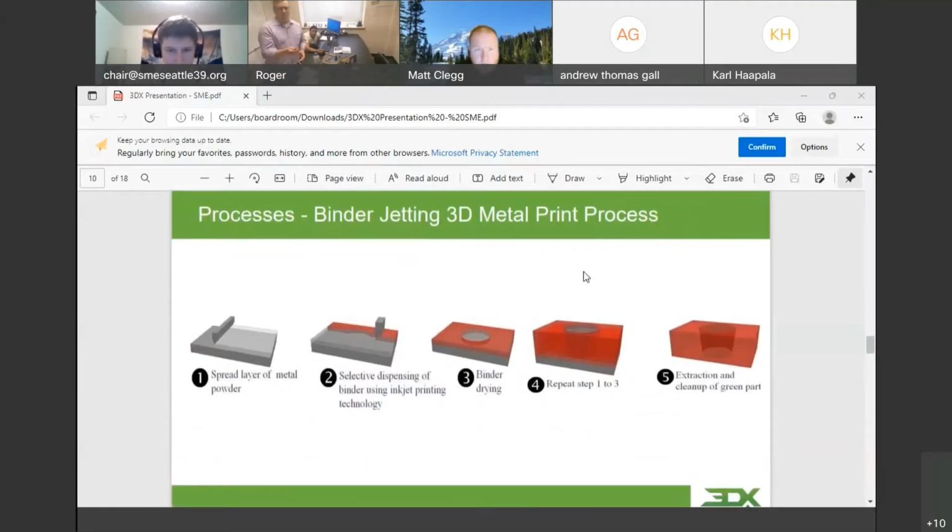This is a build platter. So what we're doing is we're using 30 micron stainless steel powder, and we're spreading that layer by layer. So that's about 1.2 thousandths layers that we're currently set up as our resolution. You can go down from 30 micron, you can take it down. It's a trade-off for time. So we like to powder really quick.